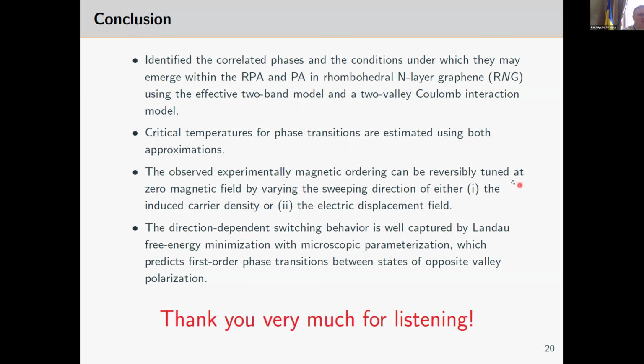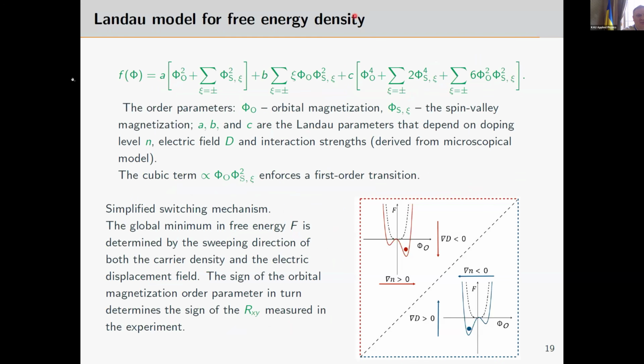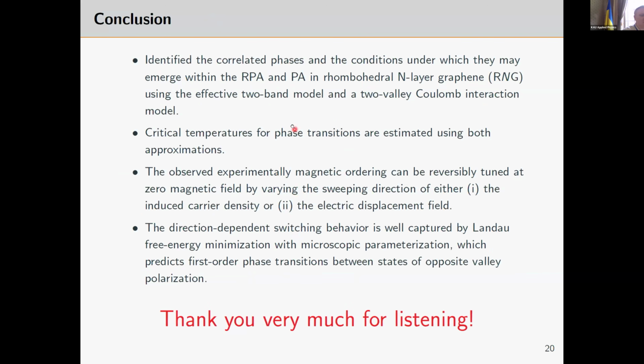The third result is experimental, so the system behaves very unusually, there is hysteretic behavior, in that the system can change the sign of anomalous Hall magnetization during the sweeps of carrier density and electric field, this is called a displacement field, perpendicular to the planes. And this behavior we, I would say, quantitatively captured by the Landau free energy model. But I should stress that for this model, all these coefficients are derived from the microscopic model, and for our consideration, it's non-trivial to take into account their dependence on the model parameters, on the displacement field, on the chemical potential, and so on. So thank you for attention.